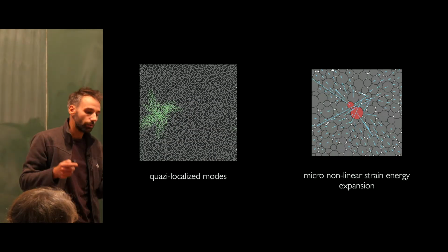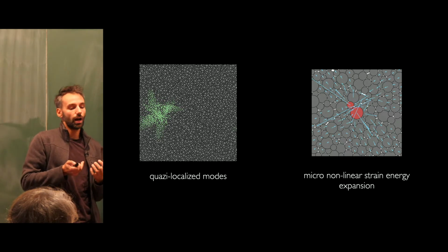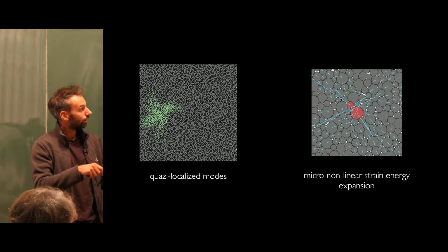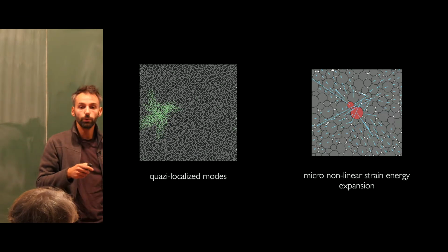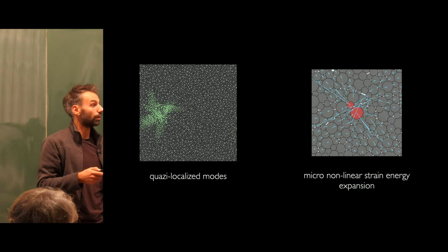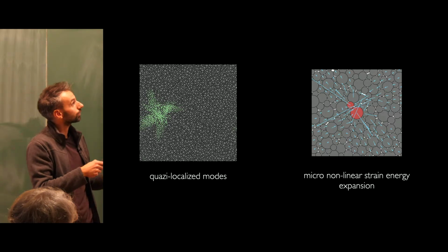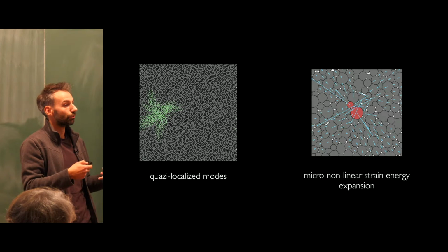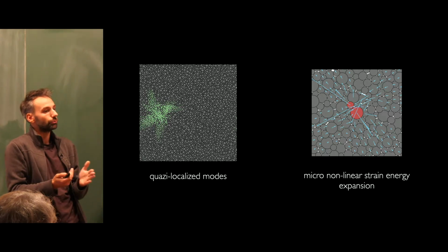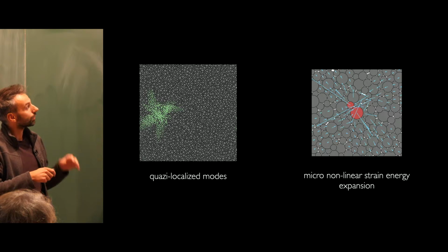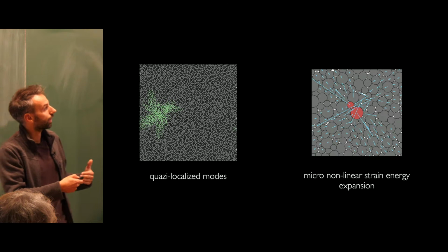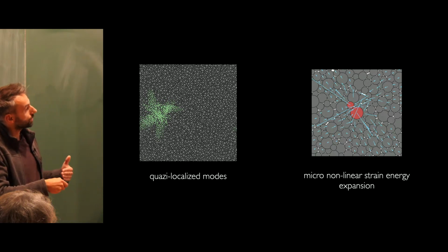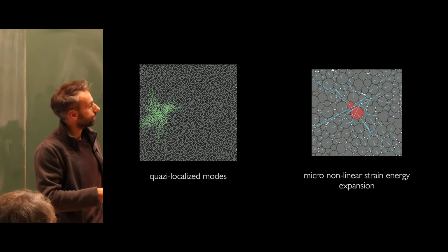What I showed you right now is only looking at the asymptotic regime. So I'm only talking about the relation between quasi-localized mode and yield stress for the weakest spot in my system. Ideally, what I would like is to be able to get all the micromechanics of the soft modes for even large deformation, not only the first 2%. That's very difficult. So we have already worked out some of the terms of this dynamics, but we are not there yet.